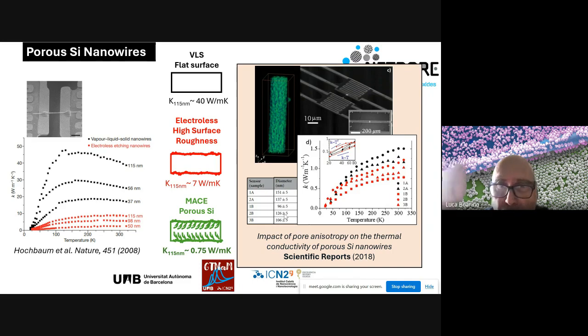We could have 50 nanometers of diameter for 75 microns. Okay, so the problem is that if you have an array, the array collapses because this is done in liquid, and if you're not applying supercritical drying or other kind of drying, all the wires are sticking together.